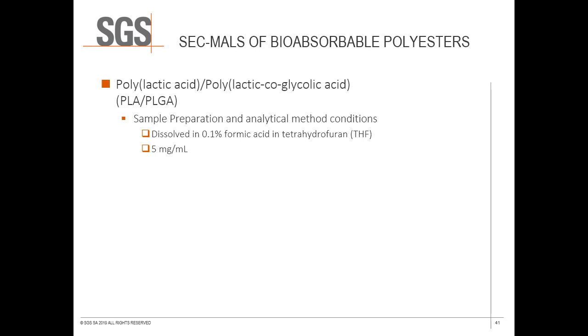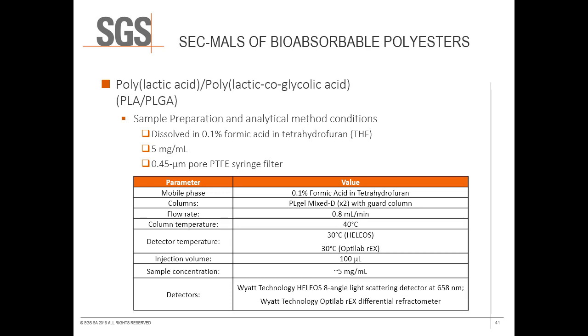Following dissolution, the samples were filtered and injected on the SEC system under typical conditions, with an SEC column selected for the expected molar mass range. One item of particular importance on this slide is the use of formic acid as the mobile phase modifier. This is to prevent column interactions that may result from acid end groups on the polymer. Let's look at a brief example of this effect illustrated.